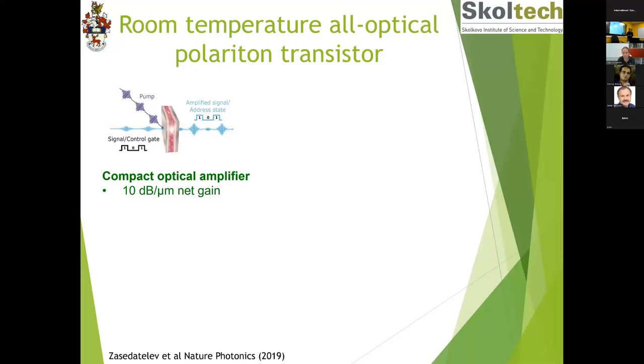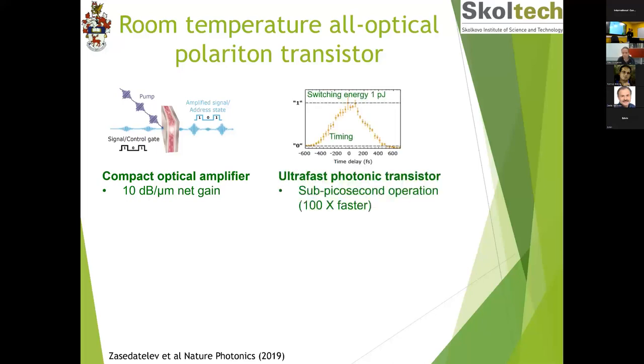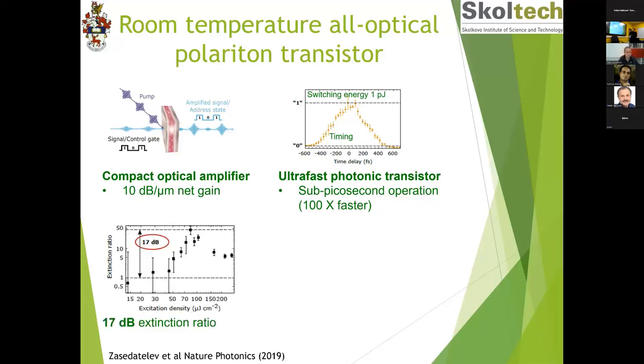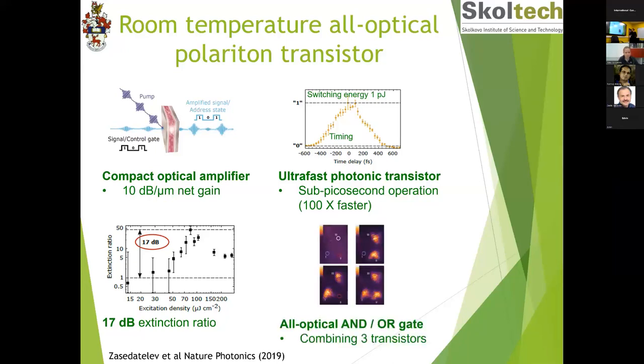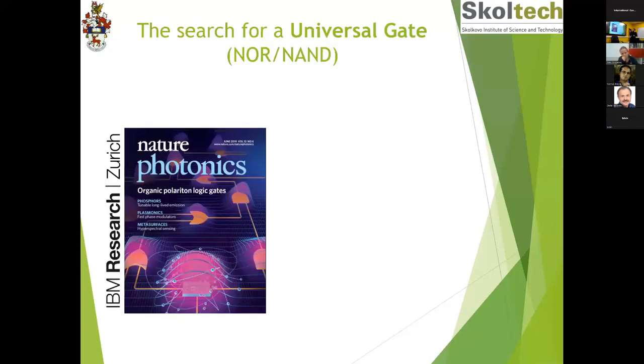Then we could show that we have an ultrafast photonic transistor with switching on and off in the sub-picosecond time scale, so a potential to operate at terahertz speeds. And then we could show that we have a very large extinction ratio, 17 dB. This is a very high extinction ratio when you're looking for the on and off state of your transistor. And then by putting several of these transistors together, we could demonstrate an all-optical AND OR gate by combining three transistors together. So we were very happy with the results that we got.